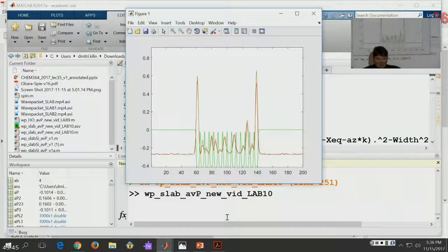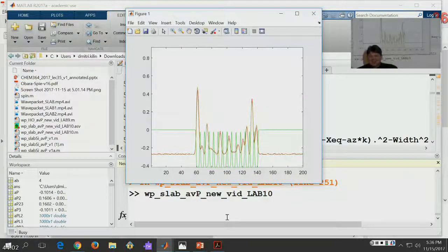So in some sense, when we want to connect this image with the particle in the box, there is a so-called Bloch theorem that you will be exposed to if you take solid state physics. If you do not take it, you probably will not see it. The wave function of an electron in a solid can be decomposed into a product of atomic wave functions that are localized on each atom, here, there, and a slowly changing envelope function.